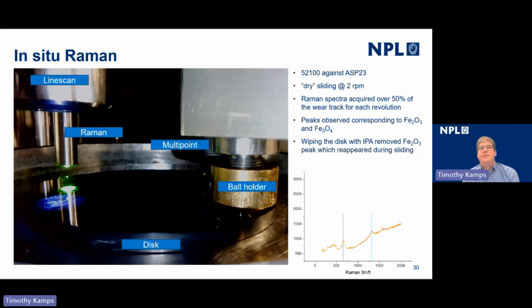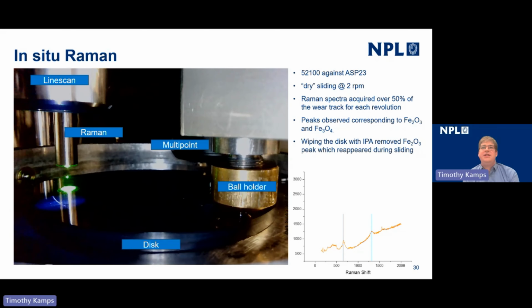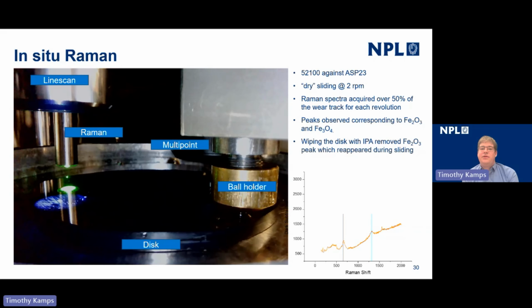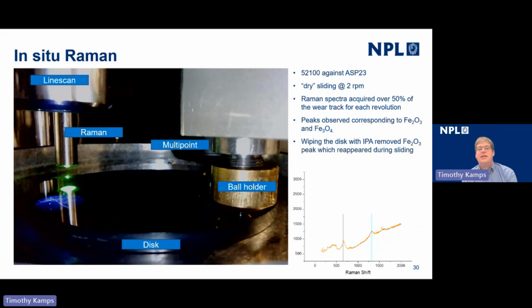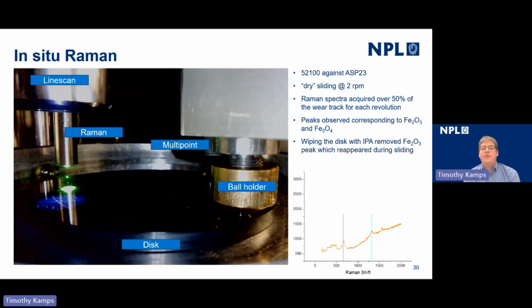One of the other sensing technologies that we've integrated into this pin-on-disc test system is Raman spectroscopy. In this case, we've got two steel contacts, a 52-100 ball bearing sliding against an ASP23 disc, and what we're looking at is the formation of iron oxide in particular.